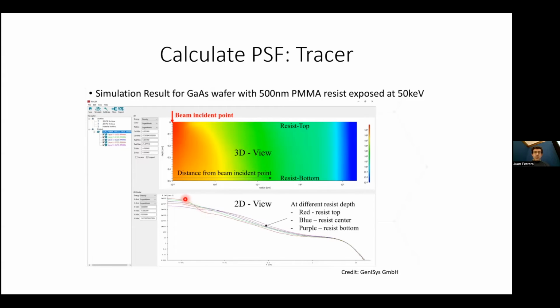Similarly here, the red line is the energy deposition at the top of the resist film. You can see that it's fairly sharp. It actually follows the radius of the incident beam. You can see an intermediate regime here where the exposure goes down gradually. You don't have the forward scattering and the back scattering alone; there's a certain amount of mixing between the two in this region. And at the resist bottom, which is purple, you can see that there has been a lot more forward scattering, and the back scattering stays pretty much the same for all layers in the resist.